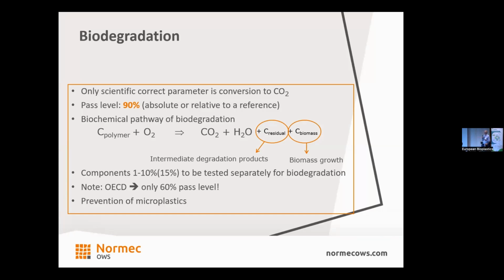And here you see a nice graph of the biological pathway for the aerobic degradation. So the carbon of the material is converted with the addition of oxygen and microorganisms into CO2, water, residual carbon, and carbon biomass. You can also see that for this lab testing, we only follow up the carbon in the CO2. That's also the reason why they say that 90% biodegradation is sufficient, as the carbon in the biomass is not considered, and it's often released only very slowly.